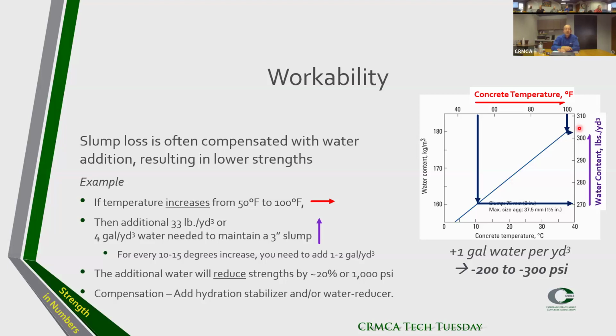So that means in the end, per 10, 15 degrees increase, we need about 1 to 2 gallons more water. If we actually add water, we're going to reduce the strength quite a bit. The general rule of thumb is you add 1 gallon of water per yard, you're going to lose 200 to 300 psi. In this example, which is extreme, we would lose about 20% or roughly 1,000 psi at 28 days for that concrete. So the recommendation, easier said than done, especially when you get to the construction site, is add hydration stabilizer or water reducer, don't add water. The water always will reduce your strength.